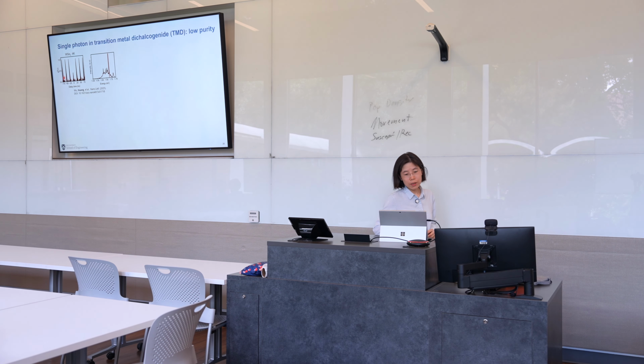Now, if you look at the photoluminescence spectrum, you can see there's a very sharp peak that corresponds to the single photon emitter, but it is sitting on this large background. This is actually commonly seen in the literature. If you look at these other literature examples, you can see the single photon emitter peak always sits on this large background. And this large background actually compromises the single photon purity.